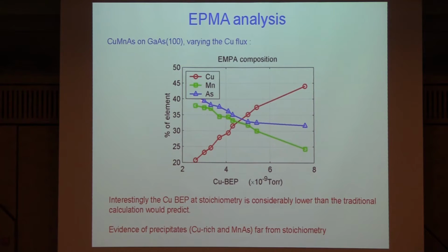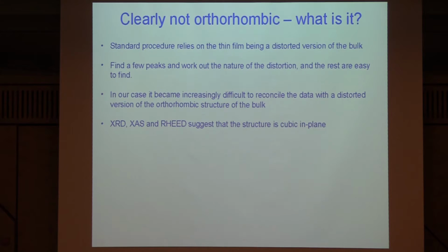The manganese doesn't behave like that. The manganese actually starts to take on more arsenic. So when you've got an excess of manganese, you actually get manganese arsenide, which we see in the SQUID. We clearly see a ferromagnetic signature. So it's clear that that's what we're growing. So basically, these are the problems that you have if you're off stoichiometry. But if you're on stoichiometry, you grow good quality material. It's also interesting for any growers around that the beam equivalent pressure is really weird. It's completely different from where we would have calculated it to be. Whatever. So, it's clearly not orthorhombic, so what is it?